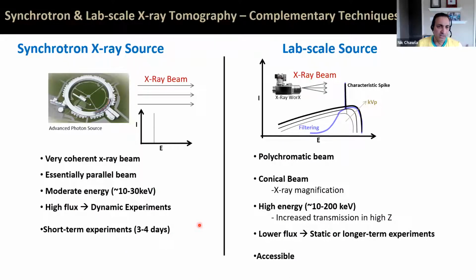Okay, so let me talk a little bit about the differences between synchrotron versus lab scale sources, because I think there is oftentimes some confusion in terms of what each kind of technique brings to the table. When we think about synchrotron source, these are monochromatic coherent beams, and they're also parallel in nature, okay? You can get to higher energies. I mentioned here moderate energy because most beam lines have this kind of moderate energy, but you can get to higher energy. And the biggest benefit of using the synchrotron source is that you get very high flux, so you can actually do the scans very quickly.